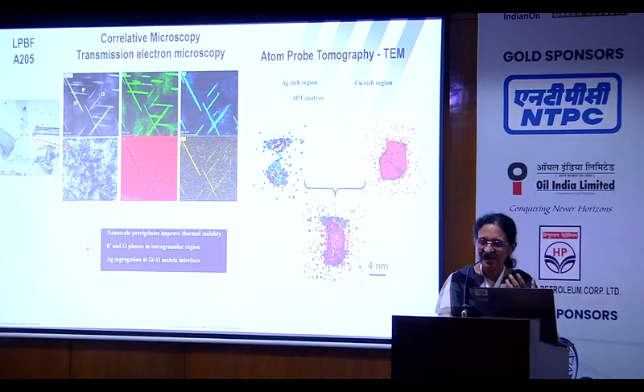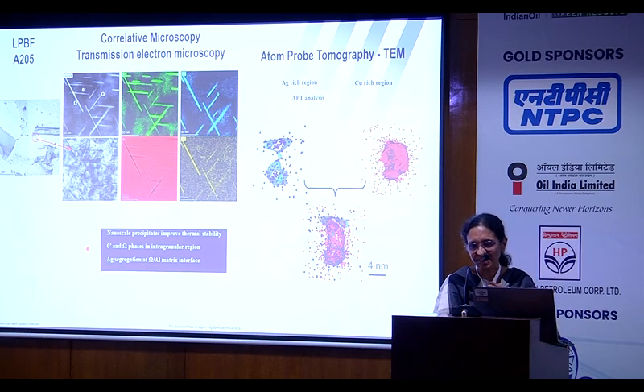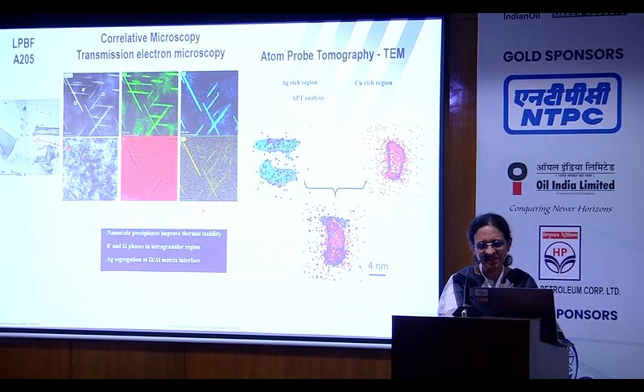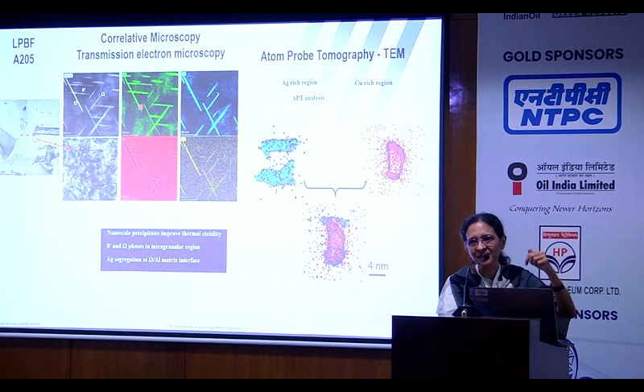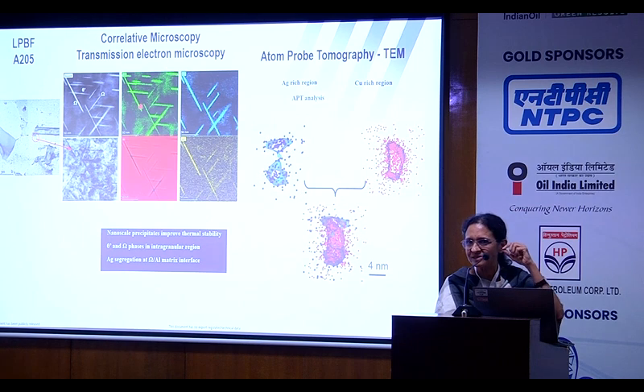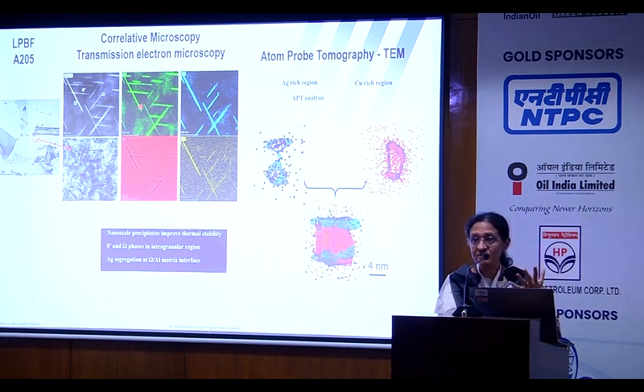Is it the same, especially in new alloy development for accelerated product development in the aero engine sector. And then we're looking at very, very advanced techniques, right here in the institute, atom probe tomography. For example, each of these theta prime aluminum copper alloy precipitates is about 2 nanometers by 10 nanometers. That is when it is coarsened.